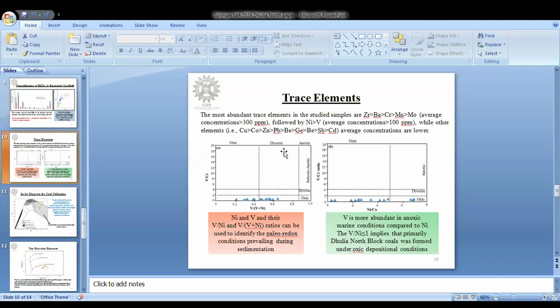Moving on to the trace elements, these are equally important like rare earth elements, because we need to know what harmful trace elements are in the coal block, as well as what can be economically explorable. So in this case, we found that in these samples, zirconium, barium, chromium, manganese, molybdenum were on average on the higher side, more than 300 ppm. This was followed by nickel and vanadium, which was more than 100 ppm in concentration, while the other elements like copper, cobalt, zinc, etc., were less than 100 ppm. So they were not significantly contributing to the concentration of the 6 to 7% which we saw, apart from the major elements.